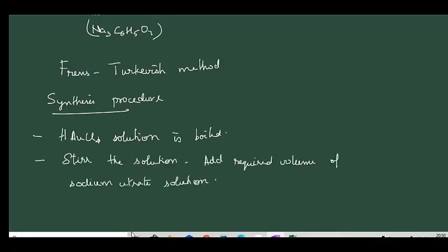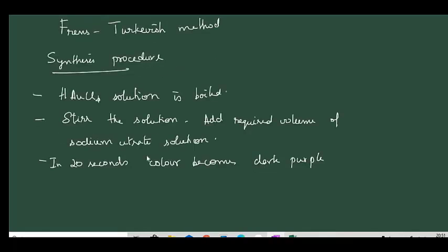Now during this process, the Au3+ is reduced to neutral Au particles, and within 20 seconds the solution begins to turn to a dark purple color. While it is continued heating, the color changes shade from purple to orange, depending upon the ratio of sodium citrate to tetrachloroauric acid.